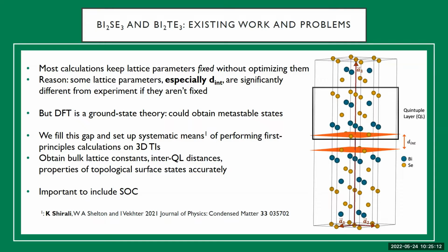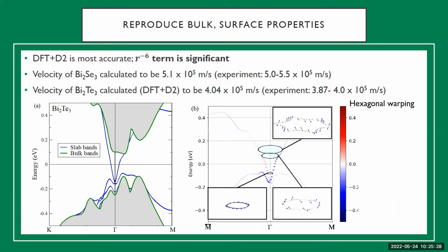So what we did was we set up a way of performing first principles calculations on these materials where we obtain the bulk and the topological surface state properties accurately. We compared a couple of different methods of including these van der Waals interactions in DFT calculations on these materials. And we found that the method which I'd mentioned earlier, the DFT-D2 method, is the most accurate, and that the 1 over R to the 6 term is significant.